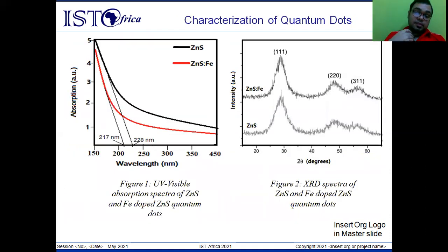After preparing this, we characterize the quantum dots, both the doped and undoped quantum dot. In the first figure, that is figure 1, we can see the UV visible absorption spectroscopy. You can observe that the absorption edge can be determined by drawing a tangent approximately from a point where there is a sudden increase in the absorption in case of quantum dots.